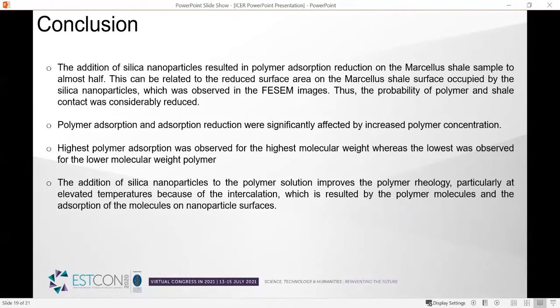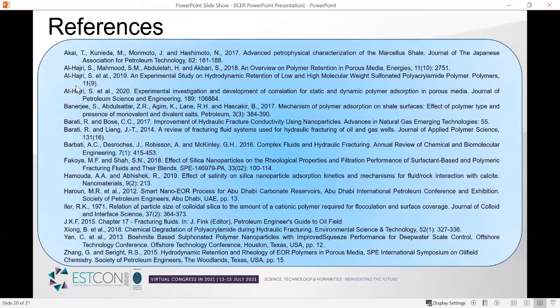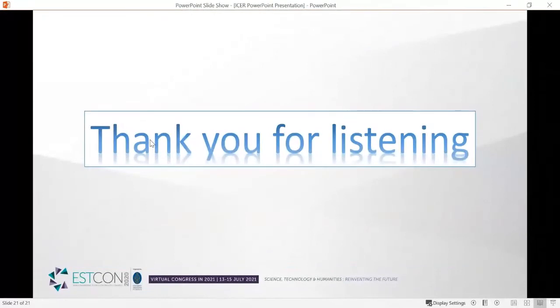And the addition of the silica nanoparticles to the polymer solution improves the polymer rheology, particularly at elevated temperatures, because of the intercalation, which is the result of the polymer molecules and the adsorption of the molecules on nanoparticle surfaces. And here are some of the references that we have used in this study. And that's it. Thank you very much for your time.